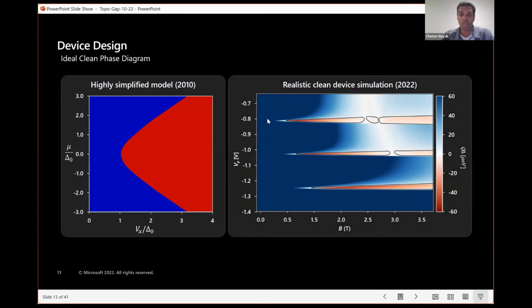So darker blues are in the trivial phase with larger gap, and darker reds are in the topological phase with larger gap. Now, what you can see is the phase diagram is more complex. Whereas there was just one topological region here, there are several topological regions. Those correspond to, as I said, the simplified model being a single subband. This corresponds to one subband, three subbands, five subbands. So with any odd number of subbands, because the wire is not truly one-dimensional, it's quasi-one-dimensional. It has a finite extent in the y direction.